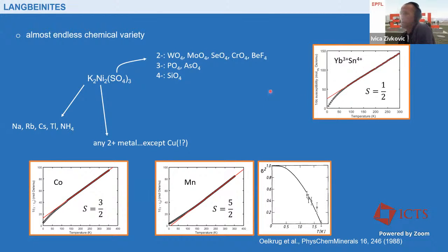There is also one example where we changed SO4 into a PO4 group. So that goes from SO4, which gives you two sites of magnetic ions in 2+, to PO4, where you can go into 3+, 4+ combinations. That means that now you are going back into a single trillium lattice state. And here you can also see that there is no indication of long range order.